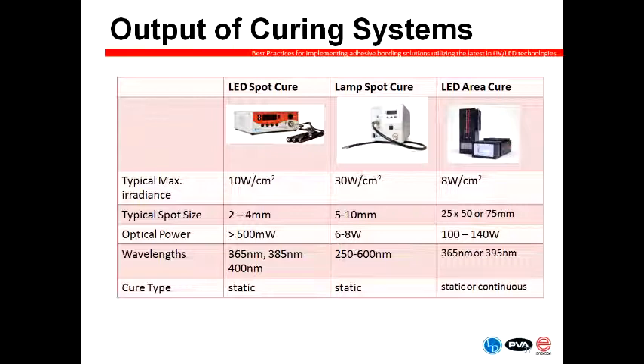So when you look at the actual optical power coming from an LED spot source, it's only about 500 milliwatts of optical power. So it's really not that high power, but because we focus it, we can generate significant irradiance in a small spot size. Now, if you look at a lamp spot curing system, you can see that you've got significantly higher irradiance available, up to 30 watts per square centimeter, much higher than you would use for most curing applications. So most spot curing systems will give you the option of adjusting the amount of output down from 30 watts per square centimeter. You can see the spot size is also much larger than available with LED, and that's because when you look at the optical power, a typical lamp spot curing system has about 10 times the optical power than an LED system. And so you have the flexibility there of using larger spot sizes, going to multiple spots, and you have the potential of also curing faster because you can now have a higher amount of power available to you for the curing process.